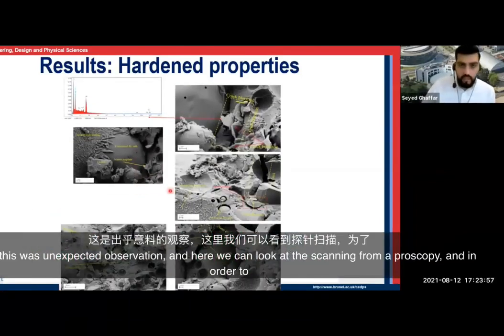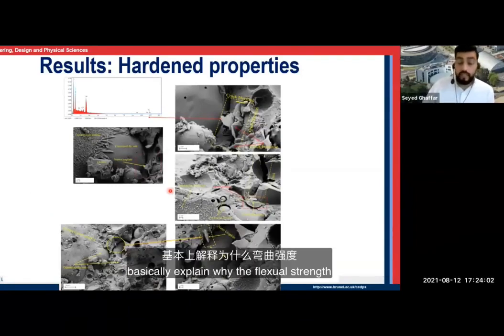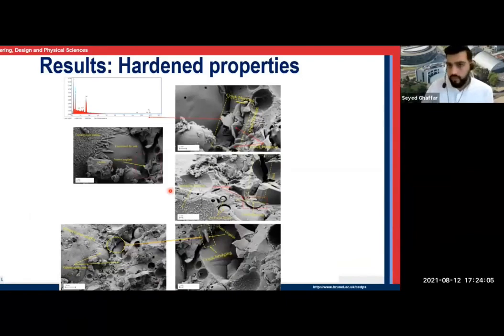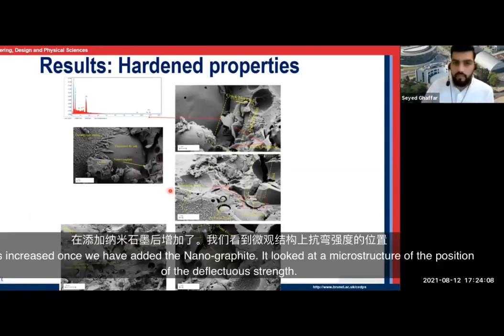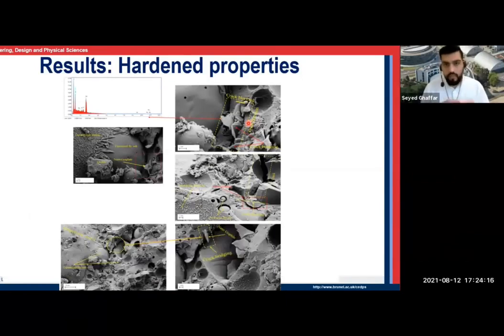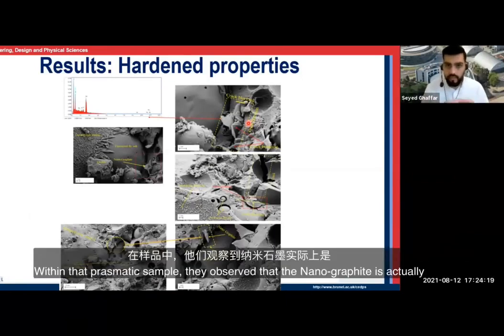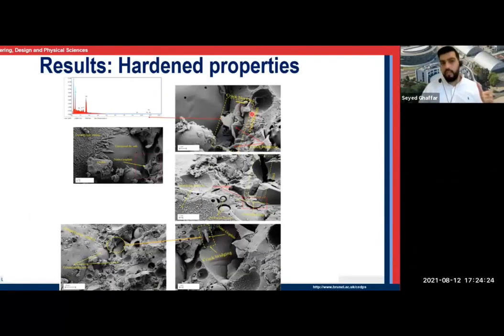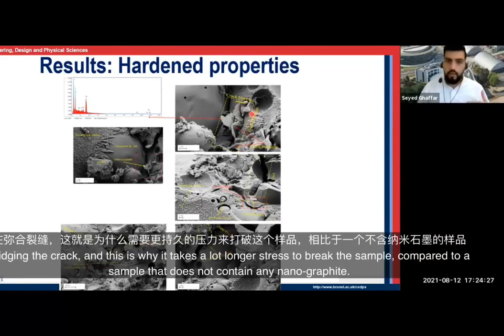And here we can look at the scanning electron microscopy, in order to explain why the flexural strength has increased once we have added the nanographite. We looked at the microstructure of the failed position after the flexural test within that prismatic sample, and we observed that the nanographite is actually bridging the crack, and this is why it takes a lot more stress to break the sample compared to a sample that does not contain any nanographite.